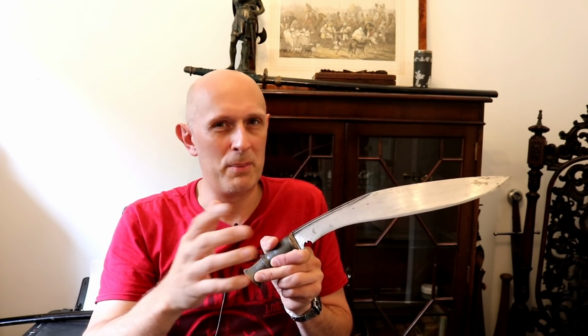What's interesting about this is that it essentially doesn't quench the back of the blade at all. It leaves the back of the blade completely soft and annealed, and only hardens the edge. So you could say it's an even more drastic version of the Japanese method, where they submerge the whole blade but the back of the blade is covered. In this case, they completely harden the edge with water. Although theoretically you could put oil in the teapot, I suppose, but I think it's usually water. So in that sense, the kukri hardening is even more dramatic in a way than the Japanese hardening.